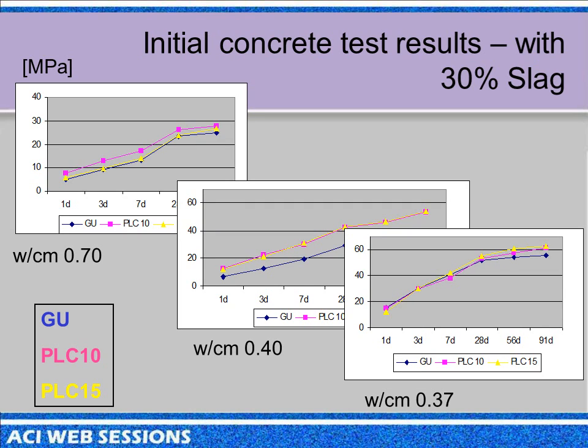And if you then take those same cements and mix them with 30% slag, for example, we're actually seeing enhanced performance, in this case both limestone mixes are showing enhanced performance over the Portland with slag. In this one mix, we're seeing less of that effect, but still, there's no case where it's worse.